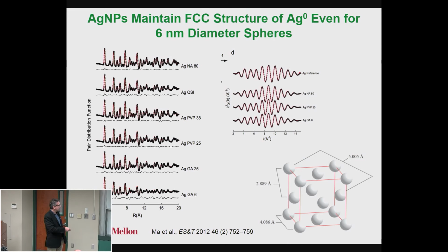They're all the same. Even down to 6 nanometers, there is absolutely no difference in these spectra, which tells me that the FCC structure of silver, which is what this is, and all these bond distances in the crystal lattice are all the same, all the way down to 6 nanometers. So this totally changed the way I thought about nanomaterials. All of a sudden, there's nothing unique. Even down to 6 nanometers, these are just small particles of the same exact stuff we've been working on before.